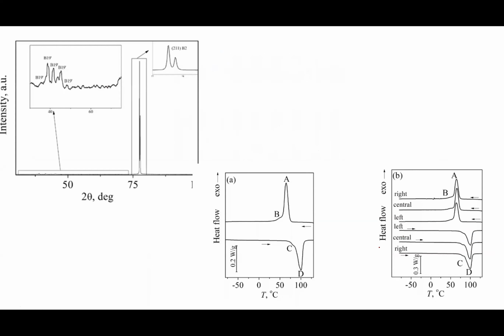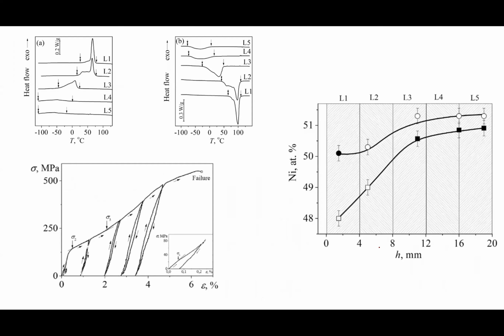Okay. Now, one of the major key aspects from the DSC analysis point of view: in the case of DSC analysis, we could get a clear martensitic transformation in these NiTi samples which are produced. In fact, we could get better clarity. We could easily map the beta phase, the austenite phase and the martensite phase with respect to the cooling characteristics. So this confirms that a proper NiTi phase was getting generated along the structures.